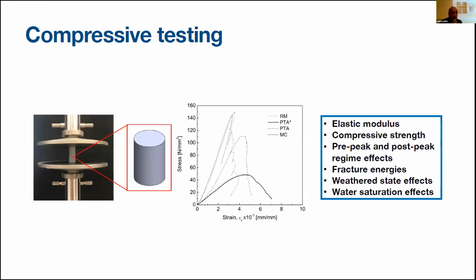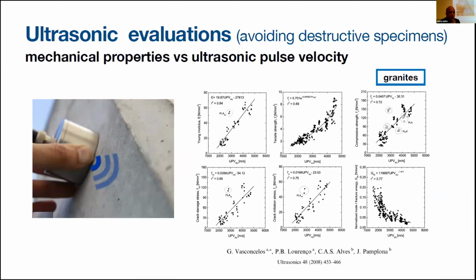Another way is we can think of compressive testing applied to small specimens of the material. This is possible. Also, in any case, some small specimens are required. In this way, you can obtain a lot of information: elastic modulus, compressive strength, post-peak softening effects, fracture energies, and so on. But also this kind of test can be avoided using ultrasonic evaluation.